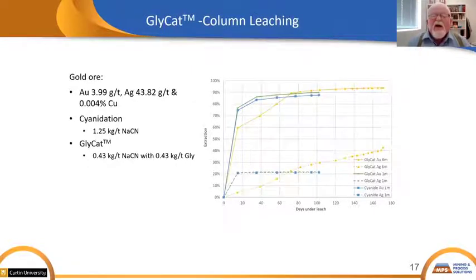Okay. This is Glycat leaching of gold ore with minimal copper. And I contrasted the leaching with straight cyanide at a much higher concentration. The yellow curves are Glycat in a 6-meter column. The blue curves are cyanide in a 1-meter column, and the greenish curves are Glycat in a 1-meter column. So in every instance, the Glycat outperforms straight cyanide at a much stronger concentration. So it's a very, very interesting thing.